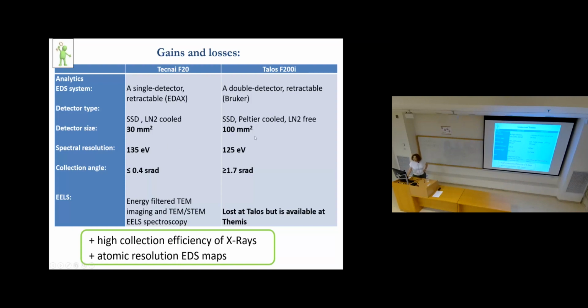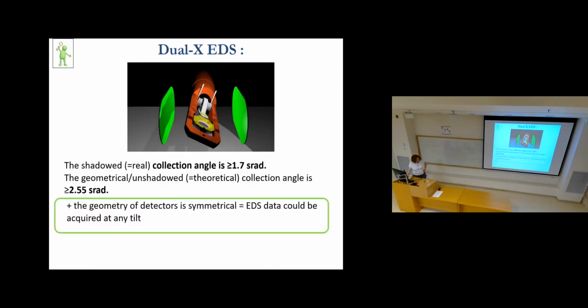So we have an SSD, so solid state detector, Peltier cooled, with a large detection area, with a nice spectral resolution. Still, we cannot distinguish between the titanium L and nitrogen K, but the overlapping of some elements is much less painful now, and the algorithms for deconvolution are much more powerful. And the key point here is the collection angle. The collection angle is so high, it could reach even 2.55 steradian.